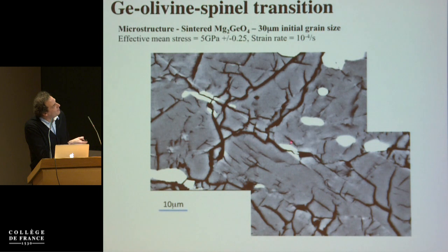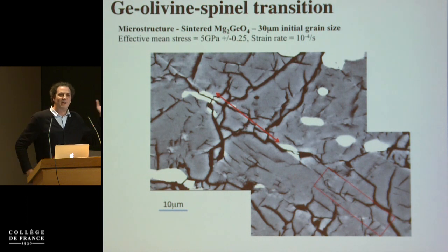This is the other part of it, and the grain has been sheared around 30 microns. So now you have a main fault on which the displacement is 30 micron, and we can zoom in front of it, and you see that the fault is marked here, but as earlier on, the faults are always marked by very thin white or lighter gray material.